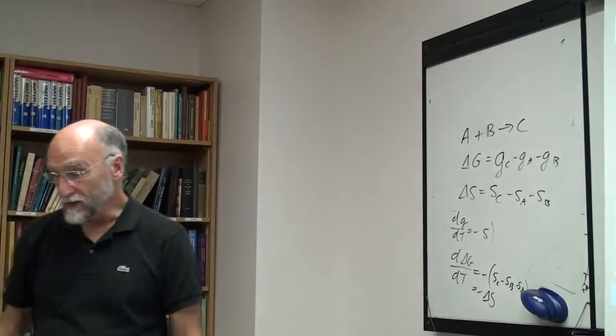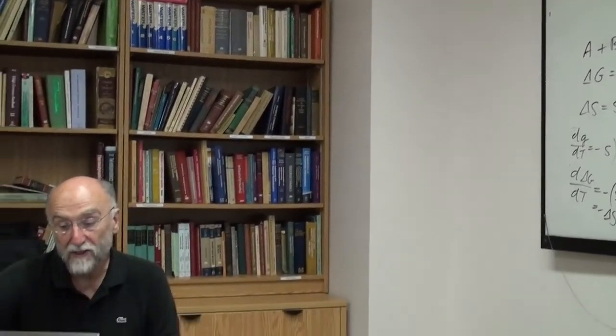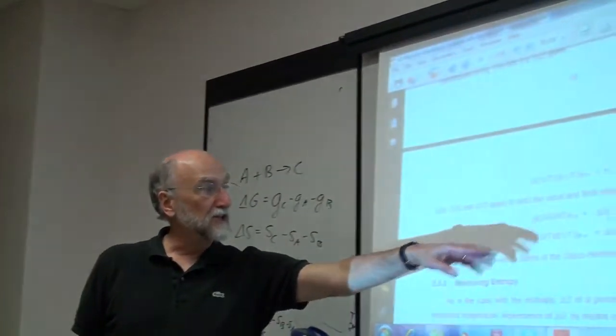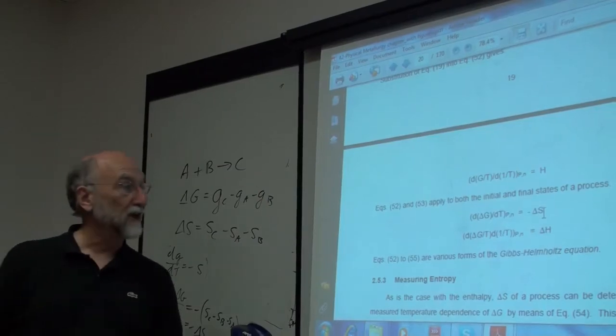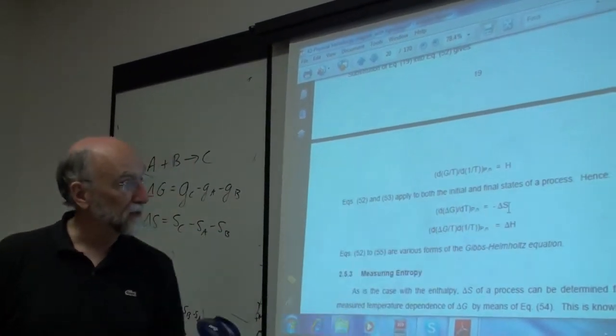Okay, so if you can write dG/dT as minus S for a pure material, you can do the same thing for any chemical reaction. d delta G/dT is minus delta S. So if you've set up a system to measure delta G, then you measure that as a function of temperature, and the slope is minus delta S. Or just rearranging it, it's the same thing. You can show that this is just, take the expression delta G is delta H minus T delta S, substitute that in here and you'll end up with this.